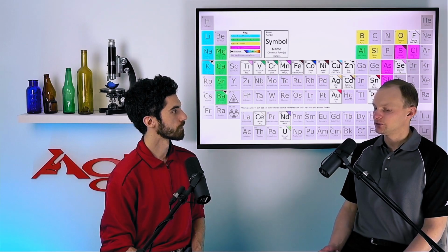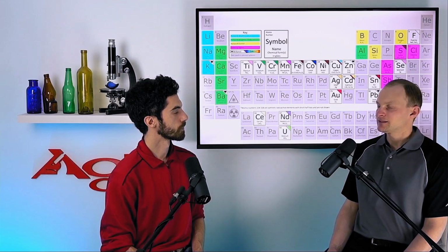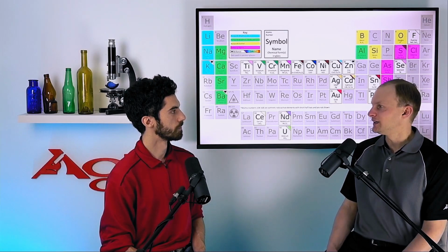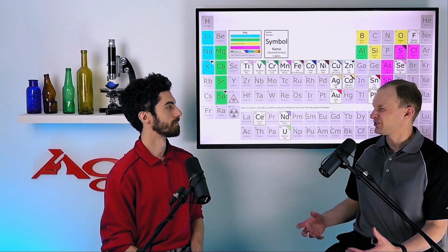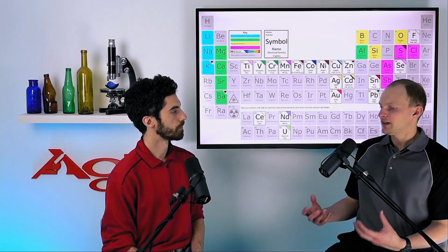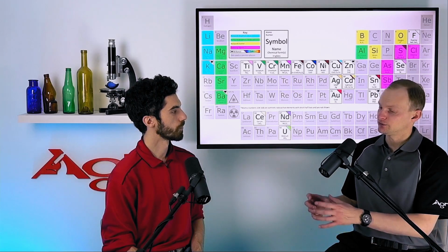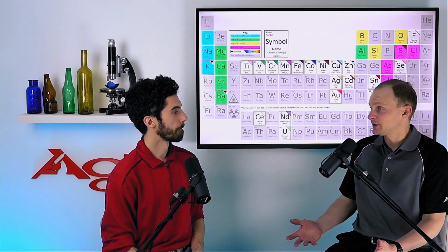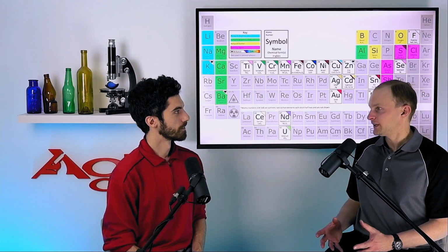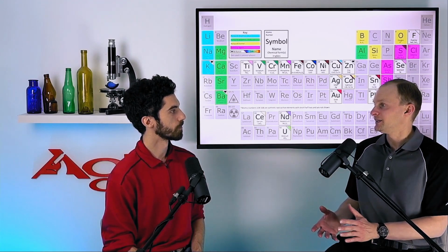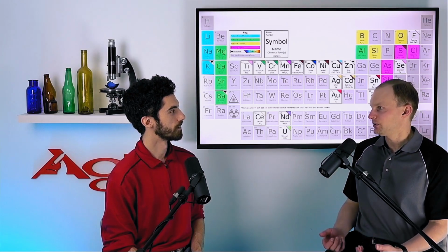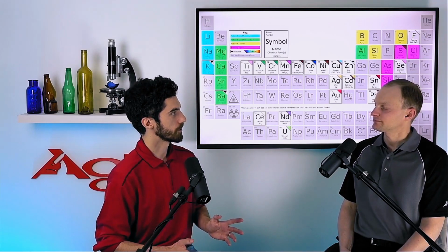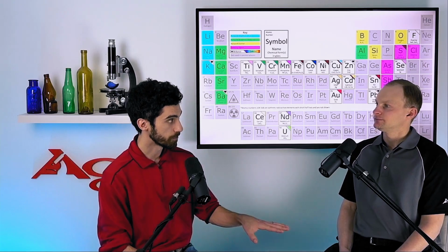But doing these specialized tests for glass products is not as easy as you might think, because a lot of labware is made of ceramics. And ceramics ultimately are usually some kind of silicate material. They're going to have the same components as the glass, so you can't use them to analyze your glass. So what are you going to do? It turns out you have to use very special techniques and special containers, typically made of platinum, to analyze glass-making components. Not many labs are set up to do that. Not many. So almost peerless, I guess, in terms of an analytical lab for glass in particular.